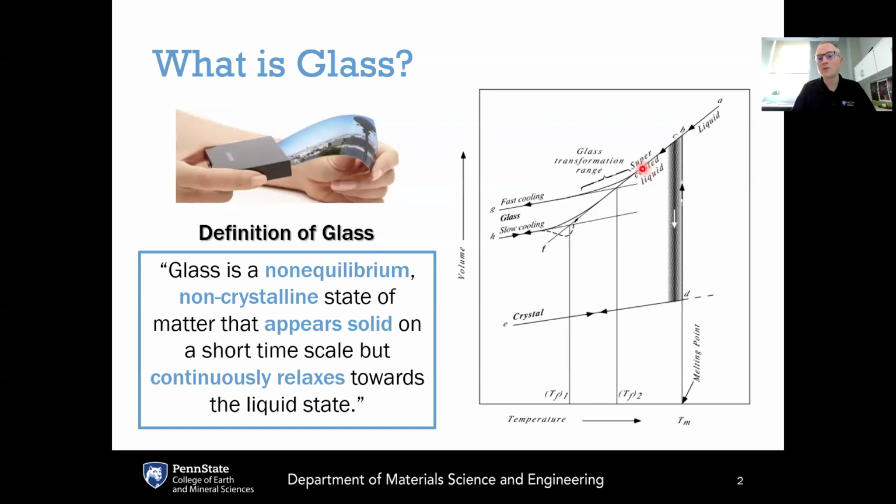So the supercooled liquid, if you just leave it here unperturbed, it's going to be stable. It's not going to change on its own. However, if it's given enough energy to be able to rearrange its atomic structure to crystallize, eventually it would undergo a first order phase transition and then drop down below here to the crystalline. Okay, so a supercooled liquid is the metastable equilibrium. The crystal is the equilibrium.